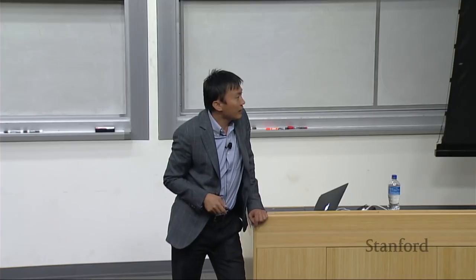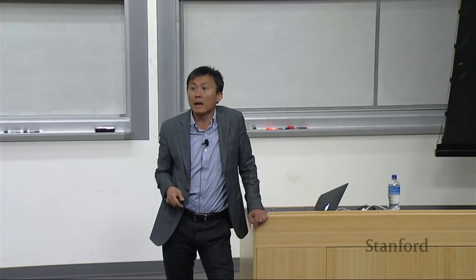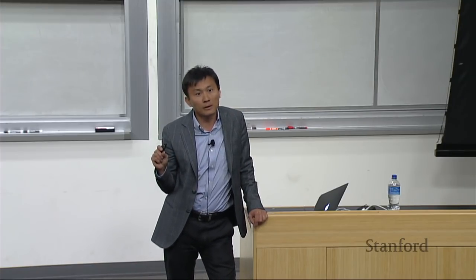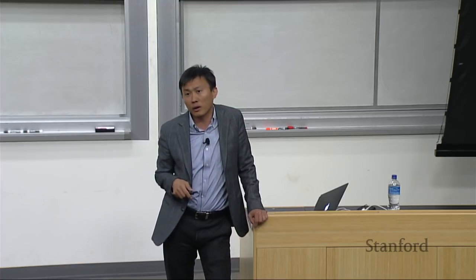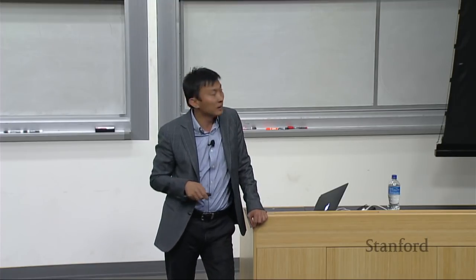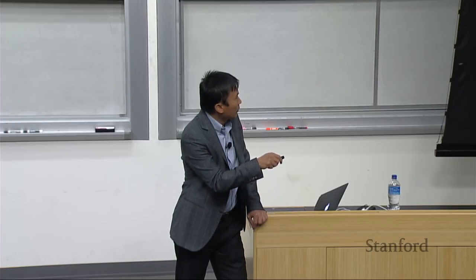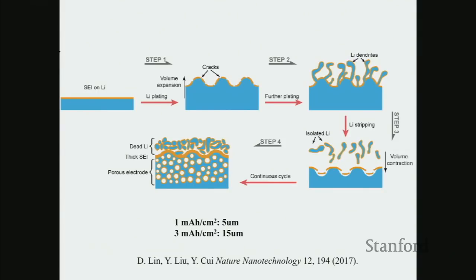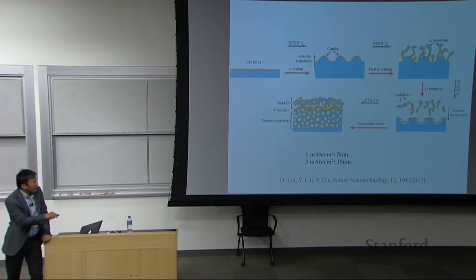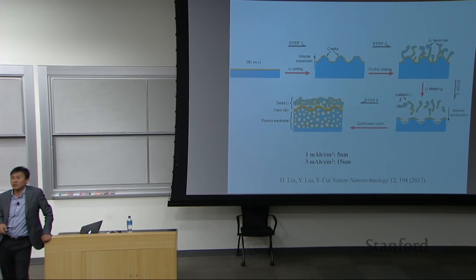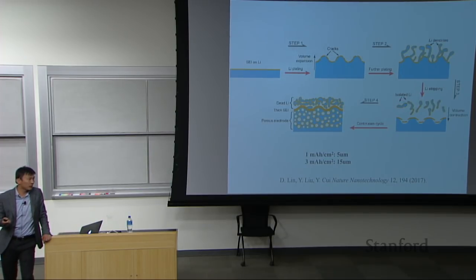You have seen in the past 10 years multiple battery incidents. Many of them are related to this metallic lithium dendrite growth, causing the battery to catch fire. And then when you strip the lithium during discharge, there's no guarantee it will come from the tip. It might go from the bottom. Then you're going to cause this filament of metallic lithium to detach from the underneath lithium foil. You use up lithium metal very fast. The cycling efficiency is very low. You build up this so-called dead lithium, and the battery also dies very fast.